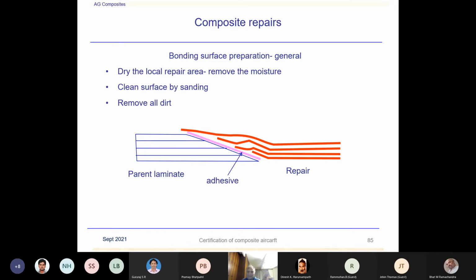In composite, generally, the moisture is removed when they are repairing, because you have to dry up the parent laminate or the part before you can repair. If there's moisture in the laminate, it degrades the joint adhesive value significantly. So, drying process and then cleaning the surface by sanding. Sandpaper will be about 150 or 250 grade. I don't remember the convention now, but an appropriate sandpaper will be used in order to sand it. And then just remove the dust and lay the adhesive.